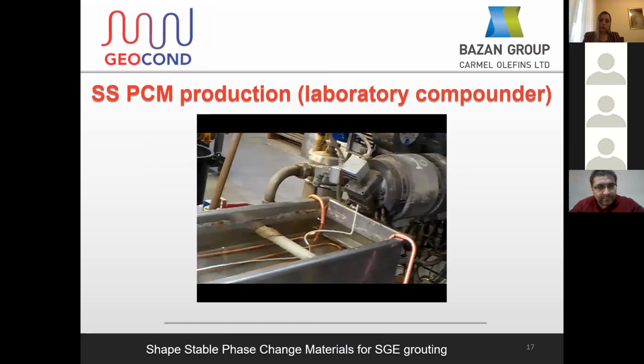For production of our PCM, we use a conventional laboratory twin screw compounder. Before I start the clip, it is quite noisy, so it may be difficult to explain what you can see. But here we see the final part of the compounder. We see a die with a single hole. We see molten polymer composition exiting the hole, entering the cooling bath, going through the cooling bath, solidifying, and finally entering the pelletization facility. So now I will start the clip, hoping that it will work.